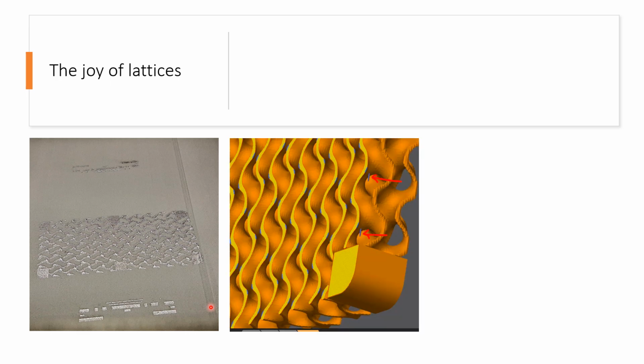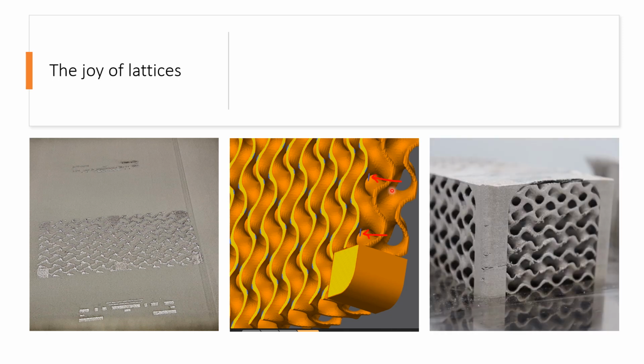So immediately went and looked at the data that we had, what the build file, and saw unfortunately that the lattice is unsupported at the edges. It's just the way it's been truncated here. And so these islands that are arrowed are completely unsupported areas, and that's a no-no in laser powder bed. And you can see this is the result. This is as far as the build got with these unsupported islands. So called it 50 shades of gray and 50 gig of data as well.